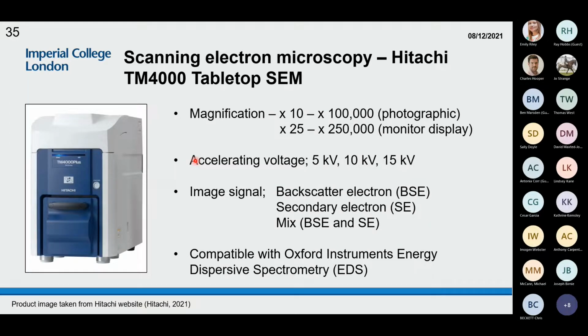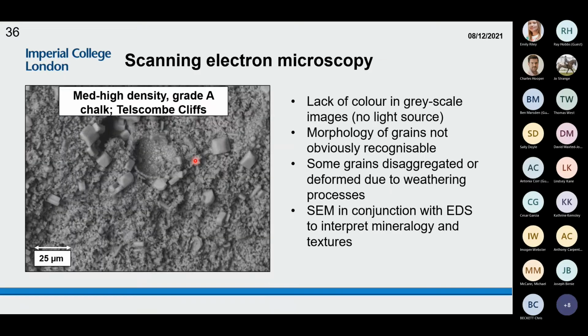So in order to check out some other aspects of chalk weathering, there are certain weathering agents in chalk, such as salt for haloclasty, which you can't see with the naked eye, and you can't differentiate haloclasty from any other type of weathering. And we know that chalk weathering basically changes the pore network. It changes the density. So if it changes the density, it likely changes the pore network within the chalk. So in order to observe this, I've been using a scanning electron microscope, the TM4000 tabletop SEM, which is compatible with an energy dispersive EDS machine, which basically allows identification and quantification of chemical elements within the actual chalk itself.